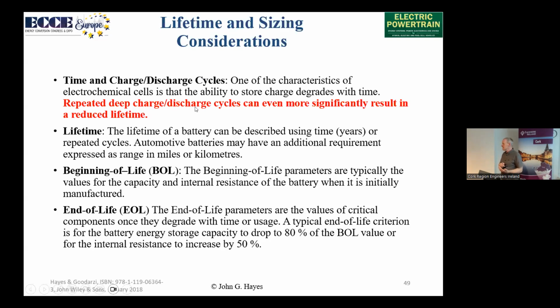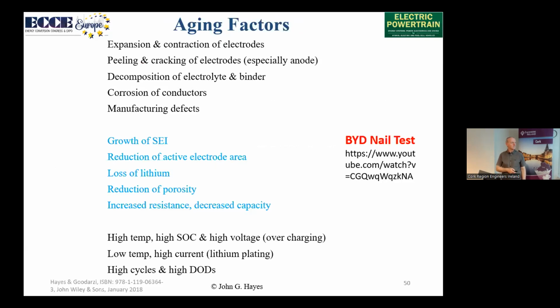The deeper we discharge it, the more that will reduce the lifetime. When we specify lifetime, that can be years, but in our world it is warranty years and it is kilometers. So the spec on the typical will be maybe 8 years and 160,000 kilometers. There will be variation in pack parameters, capacity and resistance, and those will degrade over the life of the battery. We talk about beginning of life and end of life. Typically, end of life these days, we talk about 80% of the beginning of life parameters for capacity.